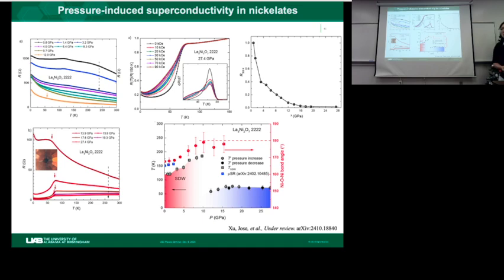Yeah, so first of all, it depends on the pressure range you want to go to. For low pressure, several GPa, the tip of the anvil can be big, and your sample can be as big as 200 micron, 300 micron. If you want to have a hydrostatic environment, you put your sample in the liquid before the freezing pressure and before it turns into solid, and then you have a pure hydrostatic environment, and then you could do all kinds of measurements.